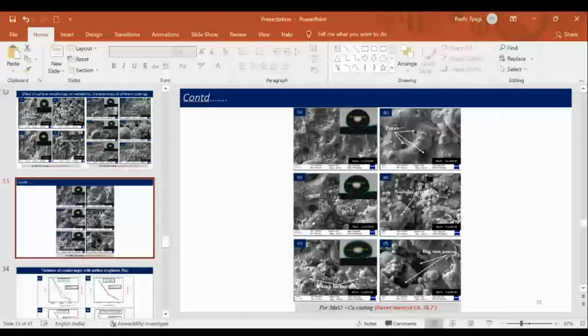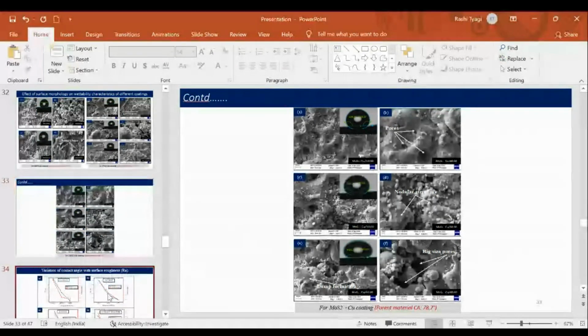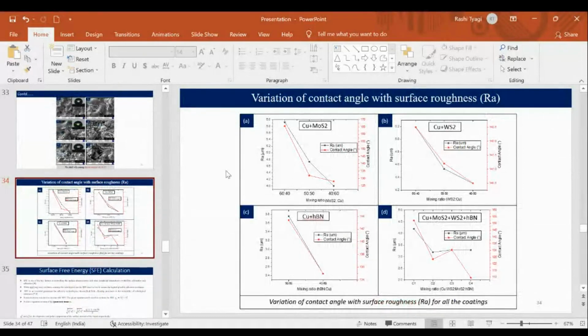Because at maximum lumps, it means it has different protrusion, different peak and valley height, so the surface roughness will be increased, and surface roughness is proportional to contact angle according to the Wenzel model. So if the surface roughness increases, then the contact angle increases. A high contact angle you can obtain. So this is the surface roughness that we have measured for different coatings.